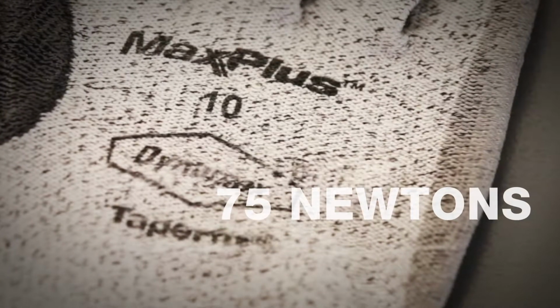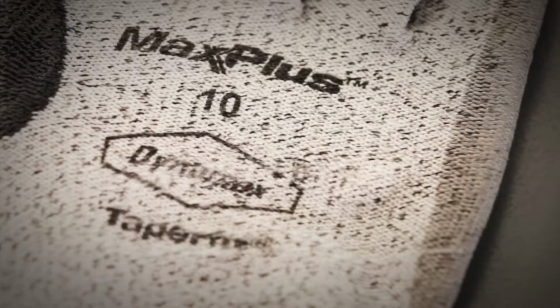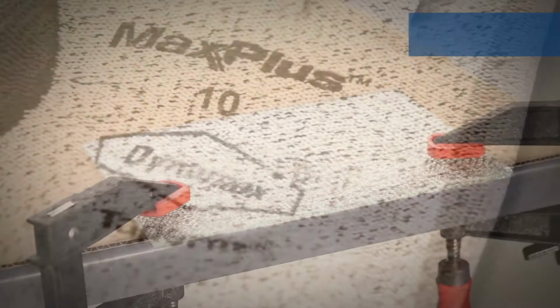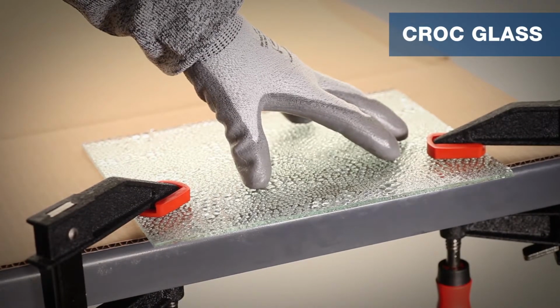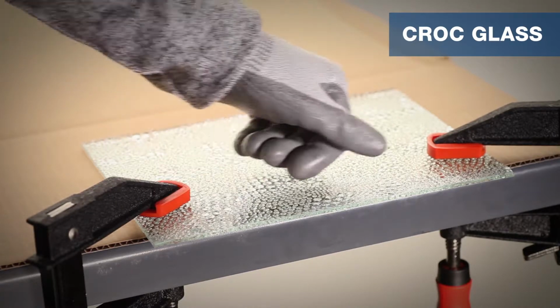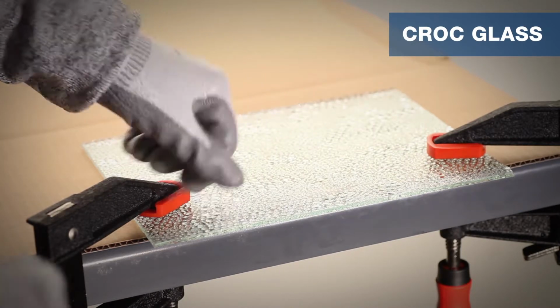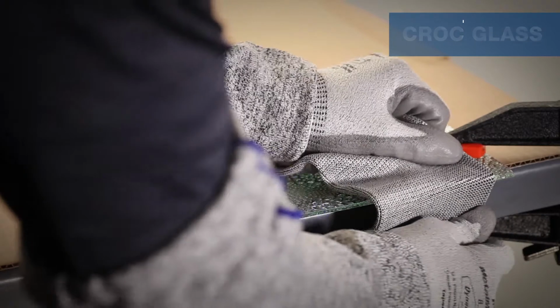The EN 388 standard has a tear test that measures the strength of a section of fabric, but the highest level is 75 newtons. The Dynamax HD yarn in this glove has a single-strand tensile strength of 168 newtons. Here is a piece of crock glass. Notice the glass beads on the surface. When this glass is cut, they form razor-sharp edges.